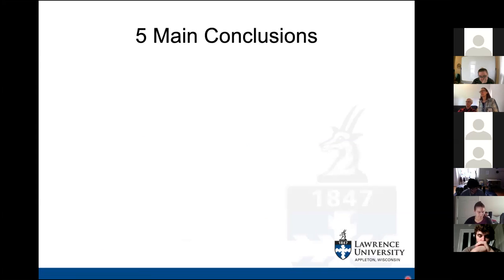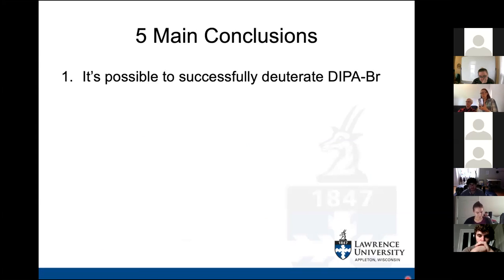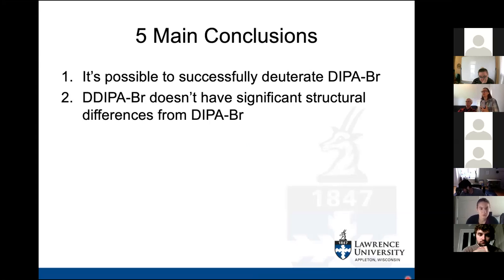There are 5 main conclusions to this work. 1, it is possible to successfully deuterate Diisopropylammonium at the amine site without deuterating the rest of the compound, as confirmed by NMR spectra. This shows that the amines prefer to be deuterated, while the rest of the compound does not. 2, deuterated Diisopropylammonium does not have significant structural differences from its non-deuterated counterpart. Both present themselves as a needle-like whitish clearish crystal, and both have similar chemical spectra.